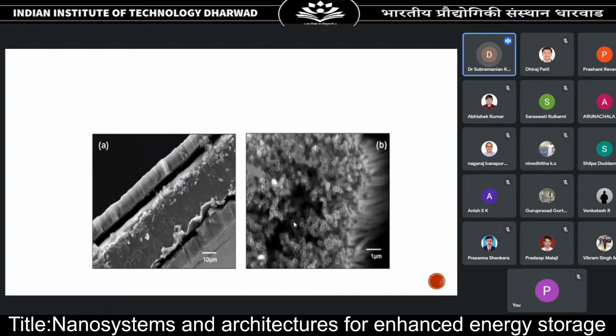This shows a high magnification SEM image. You can see the titanium plate in figure A, with nanotubes growing on either side. You can see a forest of nanotubes, and the same nanotubes are shown in a higher magnification image in figure B. You can see that all the tubules are growing out of the surface. These are all titanium dioxide nanotubules.